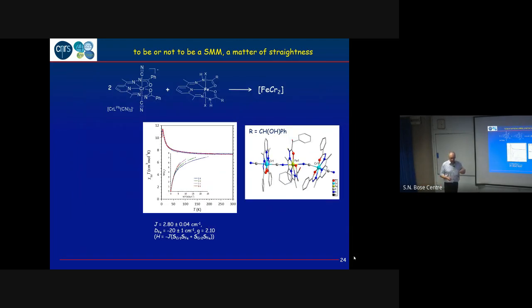So I told you my interest goes for chain compounds, but we look also at some smaller molecules, and by doing so, we realized something. This is what I would like to comment on here. So these are, let's say, the two building blocks we are using. This is the one with iron that introduces the anisotropy, and this is a chromium cyanide that is used as linker, and that will provide ferromagnetic exchange interaction. So when you do this reaction in given conditions, you end up with a trinuclear species that is shown here. So you have two chromium linked to the iron.